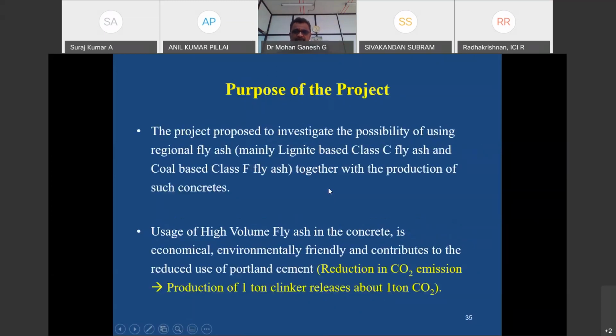For this project, we used a lignite-based class C fly ash, which was obtained from the Neyveli Lignite Corporation, and class F fly ash, that is low calcium fly ash, from the Ennore thermal power plant. Using a high volume of fly ash in concrete reduces the consumption of cement as well as CO2 emission. This is a thumb rule everybody knows: production of 1 ton of clinker releases 1 ton of CO2. So with 50% replacement, nearly half a ton of CO2 we can minimize.